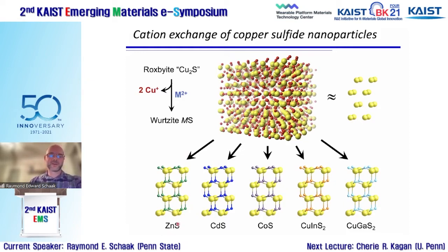This is the product of a zinc 2+ exchange, zinc sulfide exchange with cadmium 2+, get cadmium sulfide, cobalt 2+, get cobalt sulfide. Indium 3+, you actually don't go to completion. There would be a complete structural change, which is a little bit prohibitive. So you end up getting copper indium disulfide. Gallium exchange with gallium 3+ gives you copper gallium sulfide.